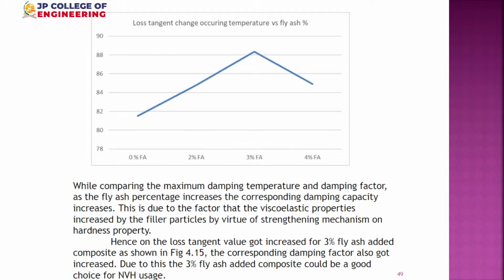Okay, so again we checked how this changes with respect to temperature. Even if we go to high temperature, how the damping behavior changes, again we could notice the same trend. Therefore, the better damping is observed in the 3% fly ash at all temperatures, even at high temperature. So by strength, by damping, and also minimal water absorption and high temperature stability, we felt this 3% fly ash with 700 nanometer gives the optimal property. Next slide, please.